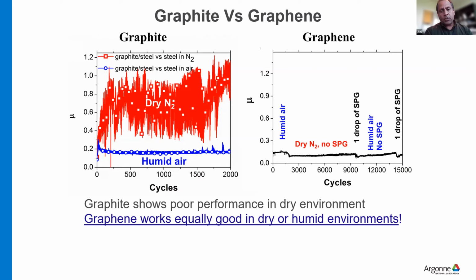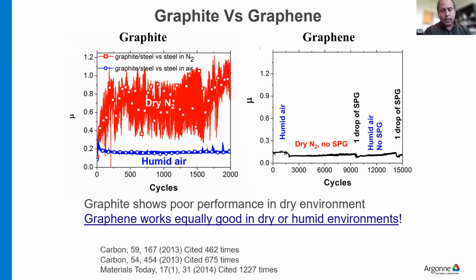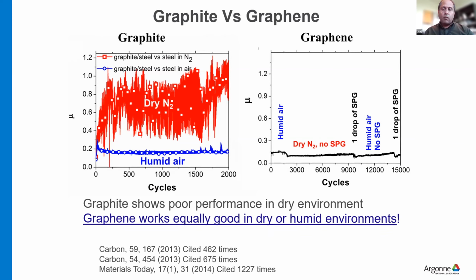So this is one of the characteristic features of the graphite. But when we start using graphene, on the right side of this graph, in this case, we actually change the conditions from humid air to dry nitrogen, and then we see little difference in the friction coefficient. So that was the first wow moment for us. And this was a paper that we published some time back, which has been cited many times, where we show that graphene works very differently than graphite, which is the bulk behavior of the same material. And then we show that graphene works equally well in dry and humid environments. So that was the real interesting part of our investigations.